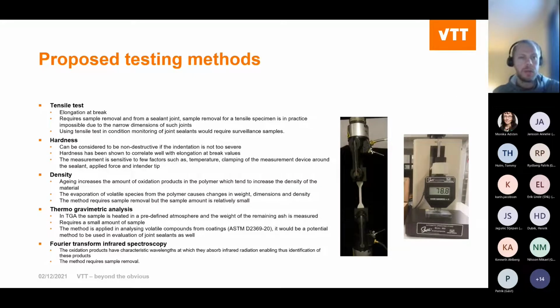Then we look into the testing methods which could be applied for this type of sealants, and here we have identified five. The first one would be the tensile test, and as is well known, the elongation at break is a well established aging indicator, but here the issue is related to sample removal, because tensile tests require a rather large amount of sample, and the reality is that the dimensions of these joint sealants usually aren't that wide, despite being long. So you really cannot remove any samples without destroying the actual seal. So here the applicability of the tensile test is limited only to surveillance samples, if such are even available.